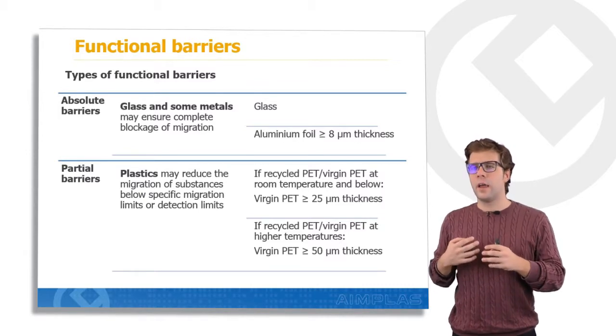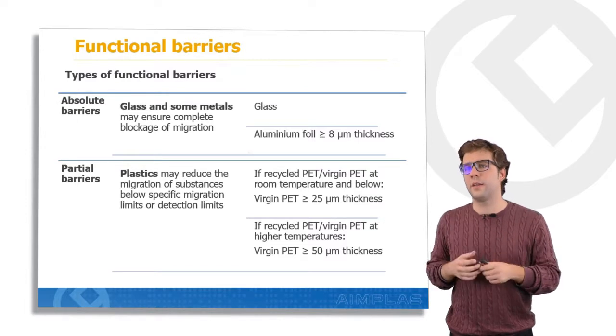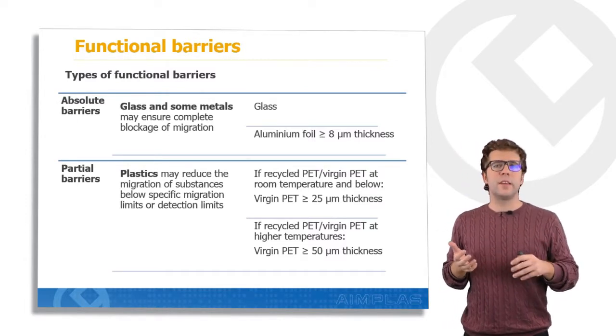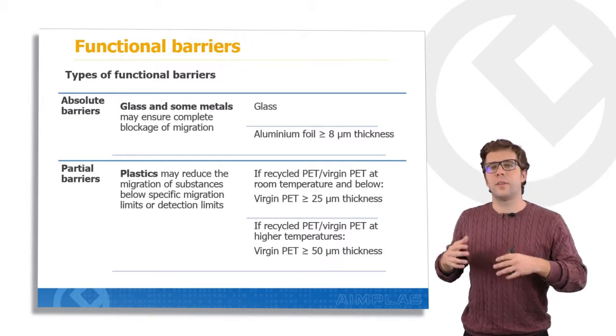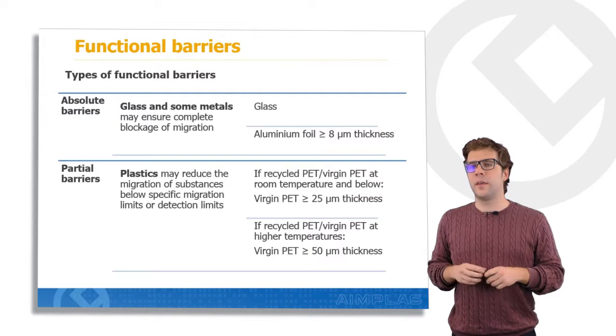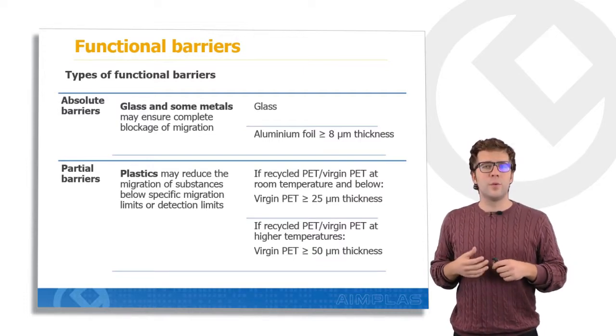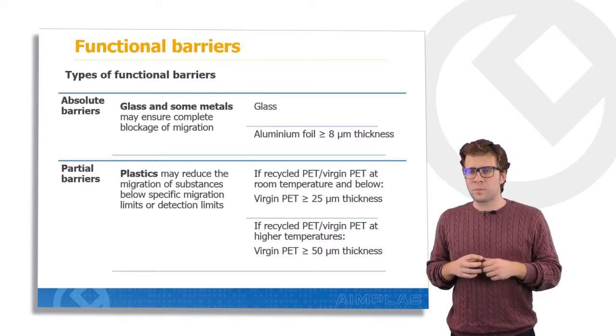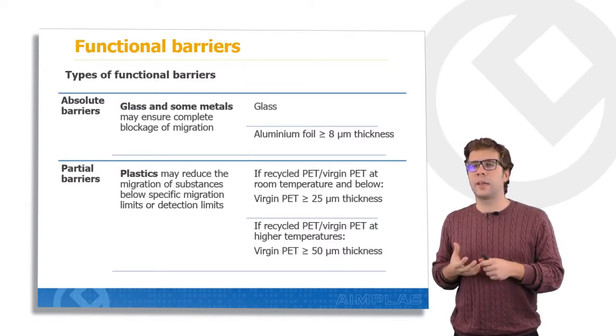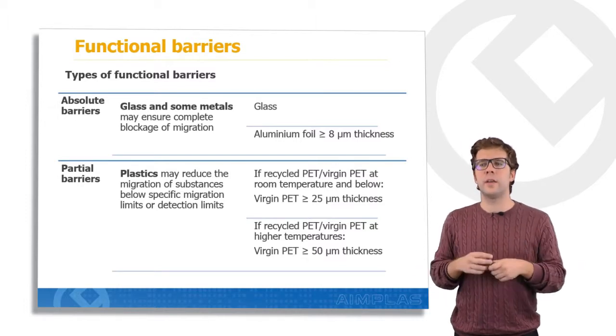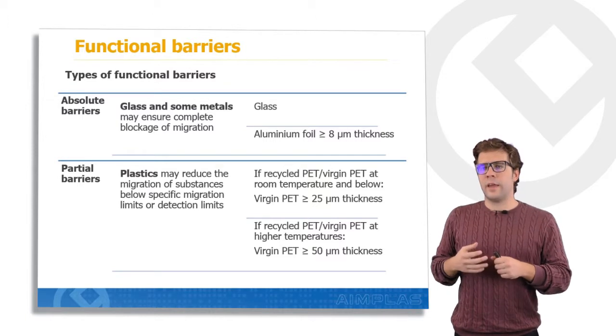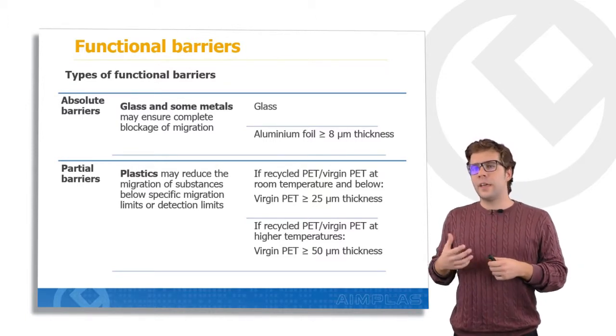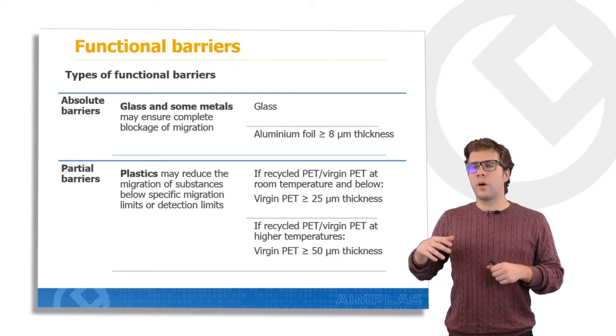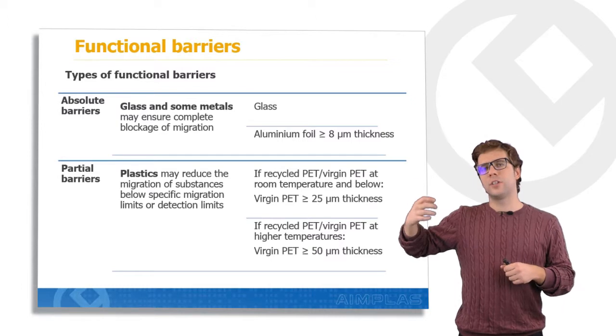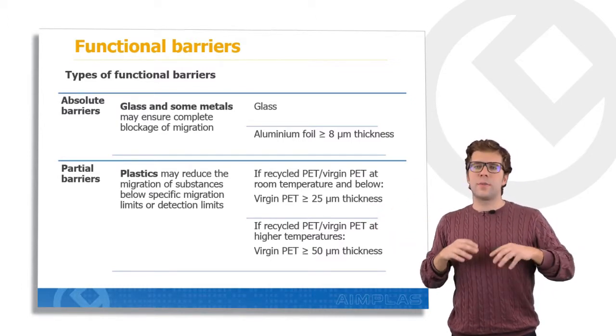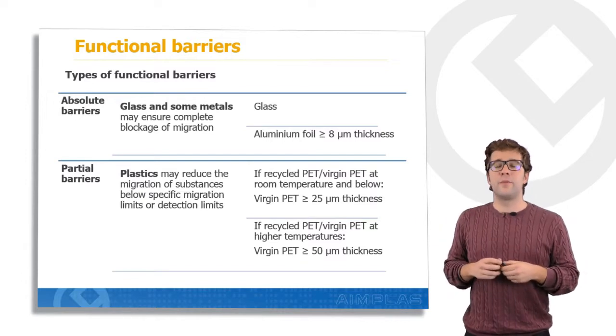Here we have some examples of polyethylene terephthalate as functional barrier. Polyethylene terephthalate is the polymer most studied as functional barrier. In this case, some studies performed by the FDA, the Food and Drug Administration of the USA, have demonstrated that virgin PET can be used as functional barrier for recycled PET at room temperature if the thickness of the virgin PET is over 25 microns. While for higher temperatures, it can also be used as functional barrier for recycled PET, but in this case the thickness must be over 50 microns.